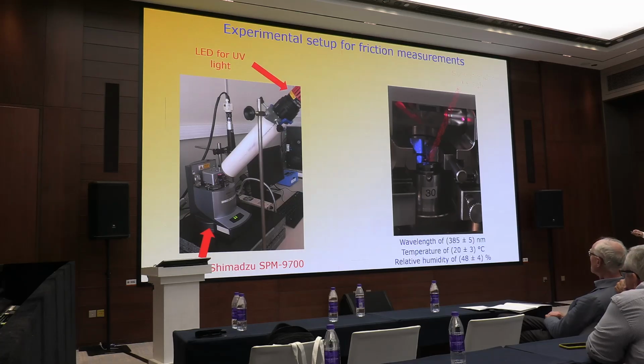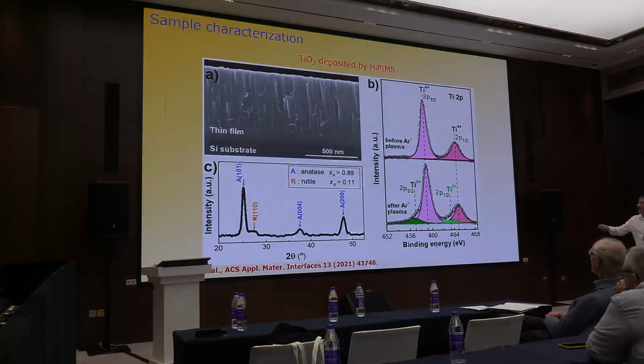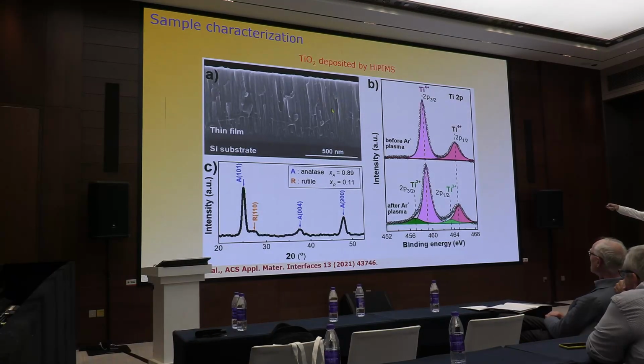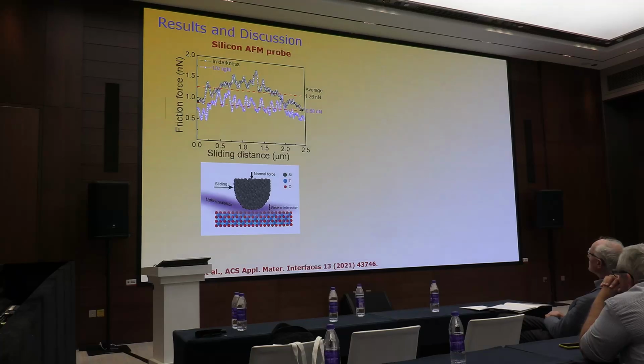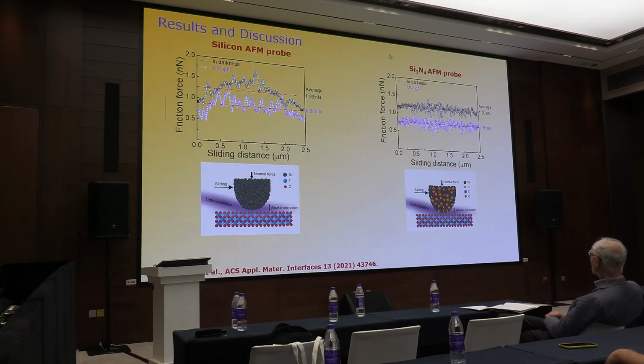Okay, let's go to the results. This is the titanium dioxide thin film, and this is the characterization by XPS and X-ray diffractometer. Here you can see the result. We use two different tips because the idea is to see the effect with different materials. We use a silicon tip, and the other a silicon nitride tip for AFM measurements.